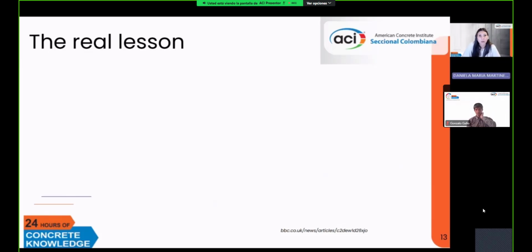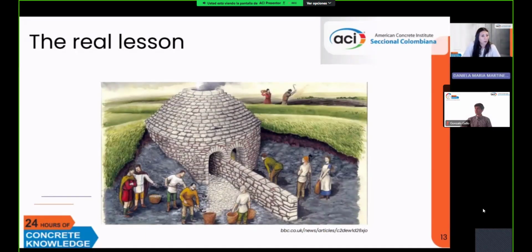Now, like I mentioned, while Roman concrete offers some reductions in CO2 and significant reduction in other harmful air pollutants, the most important observation that we can draw from our analysis is that the biggest insight is not the Roman mixture itself, but the way they used to produce it. And so in this case, the real reason why it was more sustainable was because the Romans relied almost entirely on biomass as fuel for their ancient kilns.